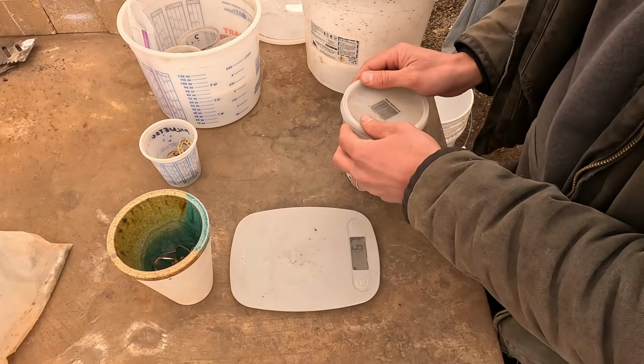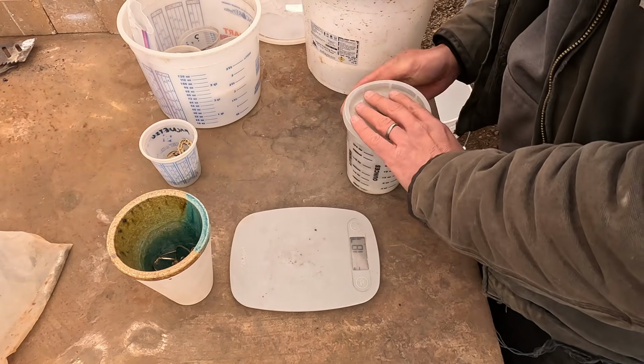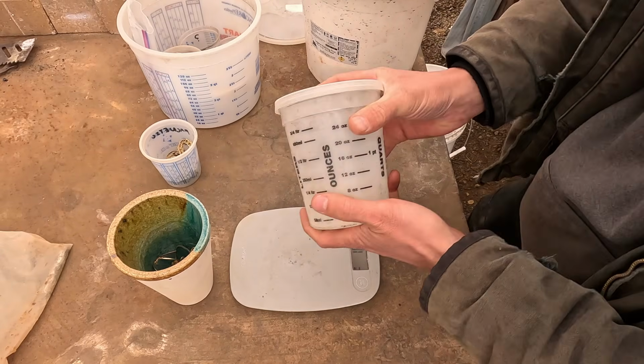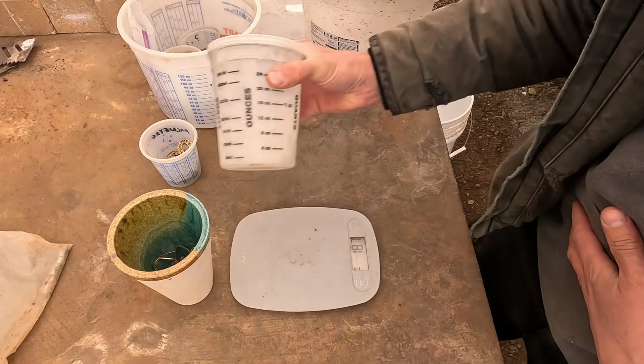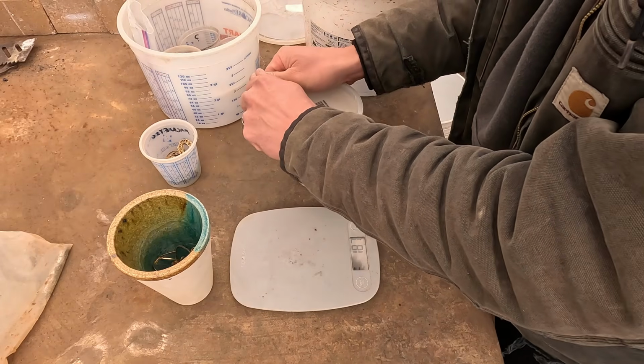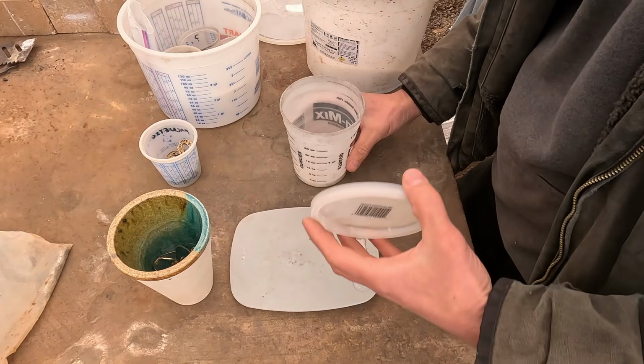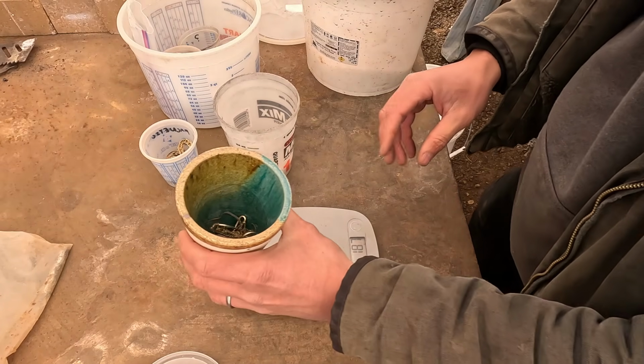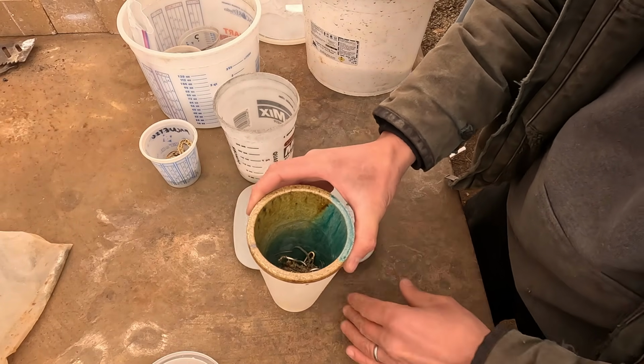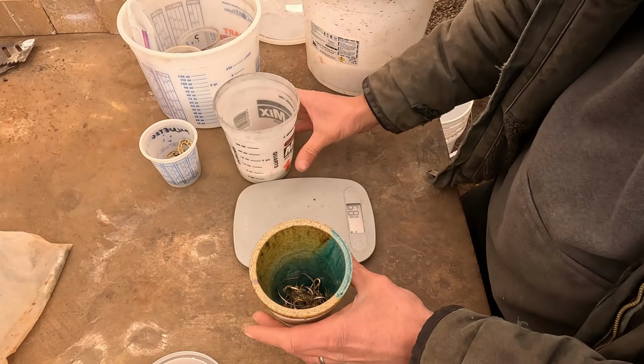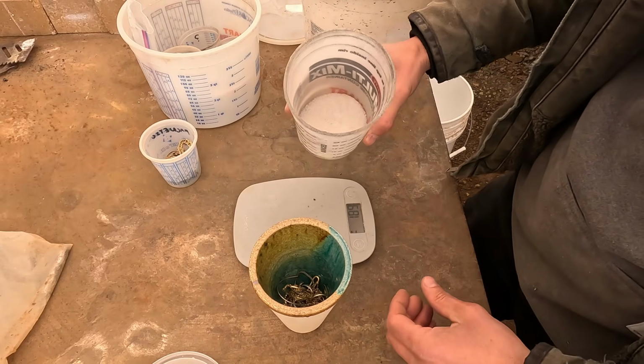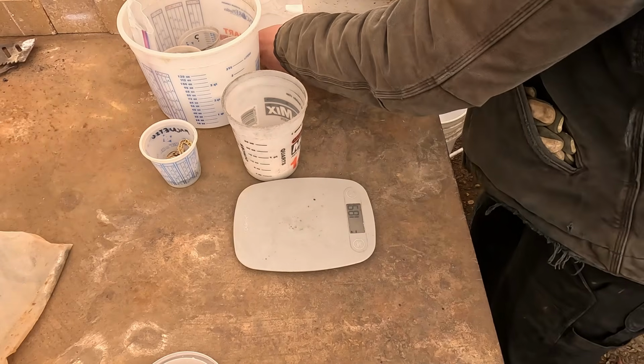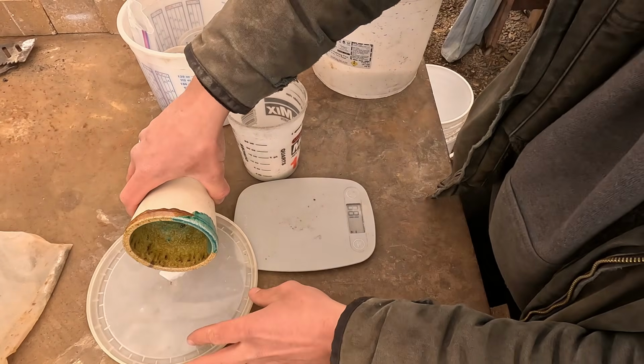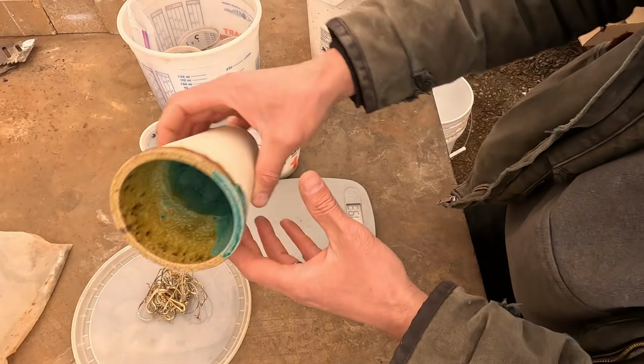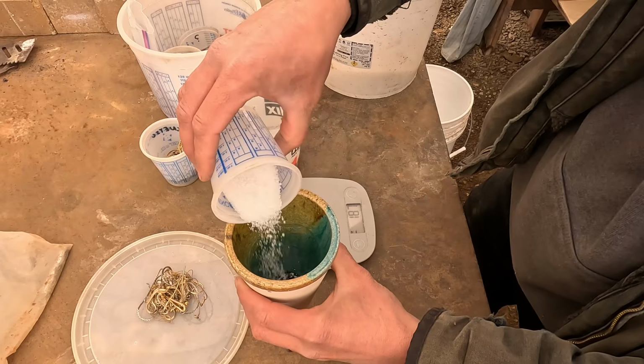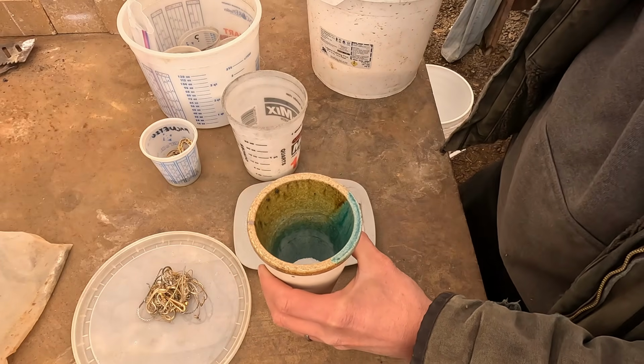Now let's mix this up so it's evenly distributed. You want that bismuth oxide evenly distributed through the flux so it can react with all the different areas of the gold fill. We should have a 30-gram bismuth button, unless there's so much oxidizer in here that it starts oxidizing the bismuth. But that might happen. Do I just want to pour that in there? I think what I want to do, let's do this. Now I'm breaking all the rules here. I'm going to put some right on the bottom. This is that flux again, so we can have some stuff right on the bottom.